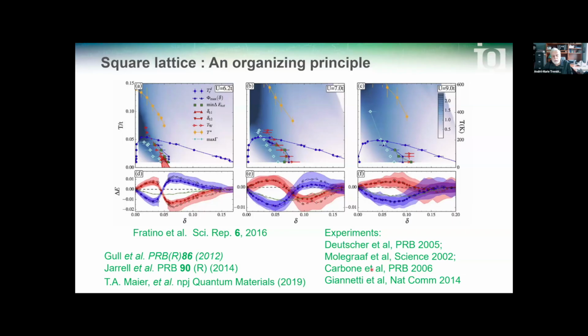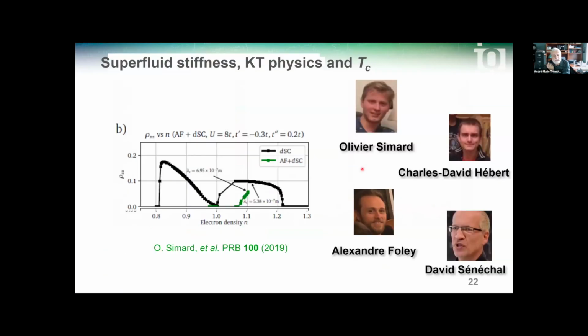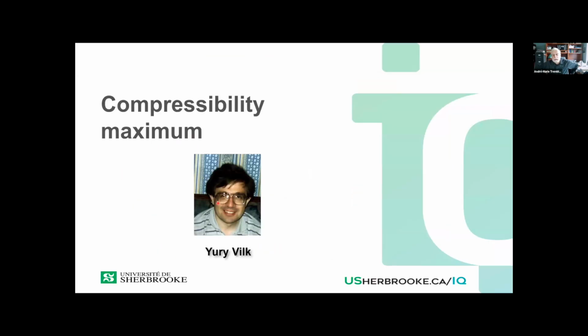This was observed in various experiments through sum rules. The blue dots are the dynamical mean field superconducting transition temperature. This indicates the formation of pairs only. To find the actual Tc, you need to take into account Kosterlitz-Thouless physics, especially in the underdoped regime. Indeed, as you can see, the superfluid stiffness as a function of electron density at zero temperature vanishes as half filling is approached. This is what leads to Kosterlitz-Thouless physics in the underdoped regime and restores the dome shape of the transition. For the rest of this talk, I will focus on the compressibility maximum that was predicted to occur along the Widom line. So I have one more participant here, Yuri Vilk.